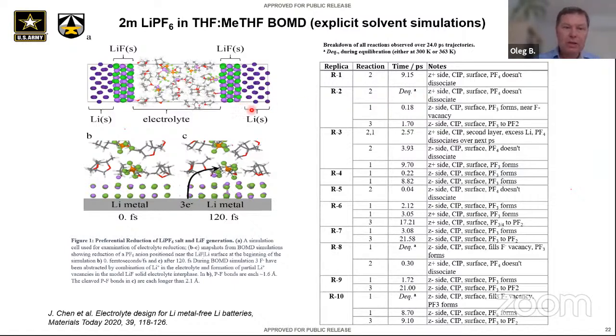What we did observe is that the most prevalent reaction was decomposition of PF6, when it would spontaneously give up 3 fluorines at the same time, not just one, leaving a local excess of fluorines on this part of the SEI, forming eventually LiF, and none of the solvents would ever decompose. So clearly that supports our previous picture that only PF6 is undergoing direct reduction on a partially passivated surface. The other observation was that if PF6 had 2 lithiums next to it, or at least 1 excess lithium, it was more activated. So clearly, as we saw before, having an extra lithium binding and polarizing anions makes a difference.